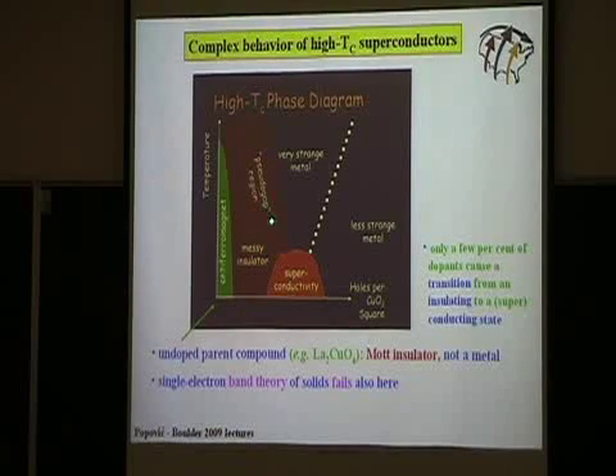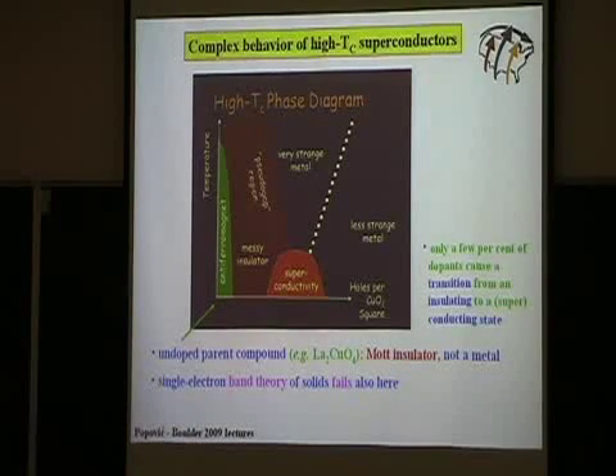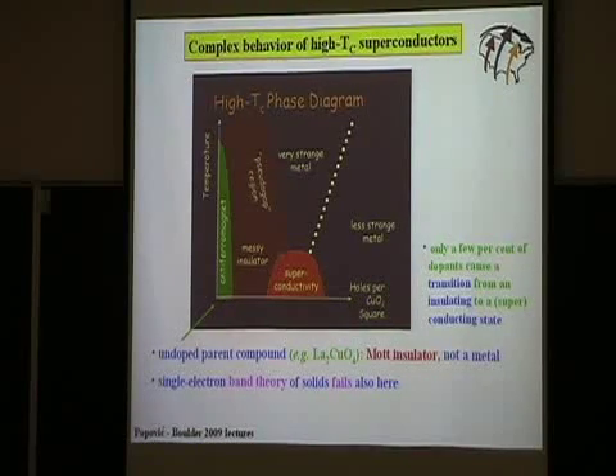Then there is a so-called pseudo-gap region, and there are lots of strange things going on even in the normal state of these materials. Now, here also, some analogy to the case of superconductors is that the band theory also fails. It fails even to predict the behavior of the undoped material, the so-called parent compound, because according to the band theory, this should be a metal, but it turns out to be an insulator. And the various experiments have shown that this is a so-called Mott insulator. In other words, the carriers, the holes, are localized because of the strong Coulomb repulsion, which is, again, of the order of, I think, more than 2 electron volts. So band theory is, again, useless here.